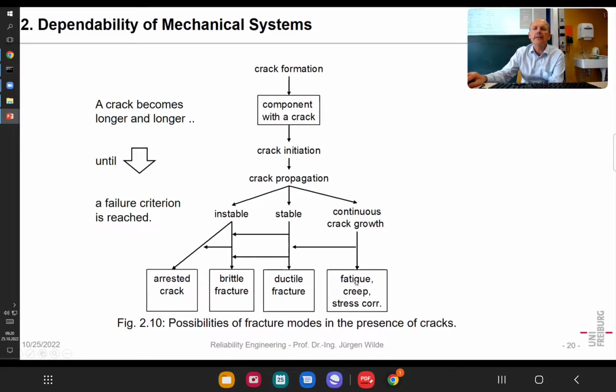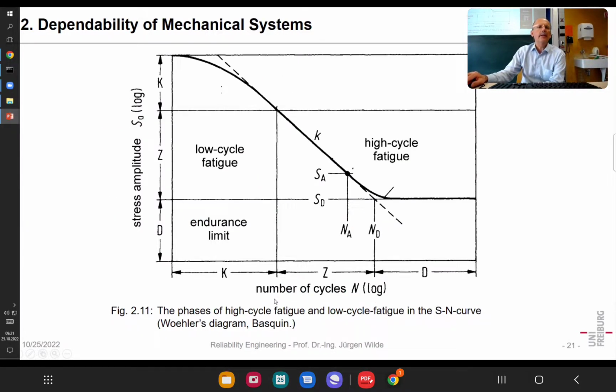Often it happens, for instance, that we have fatigue in a first phase, and in a second phase, we can have ductile fracture, that's the rest of it failing, or we can have a more brittle fracture, but that depends mainly on the material, and it also depends on the temperature. For instance, at higher temperature, materials become softer, and so they are more ductile. So that's quite complex.